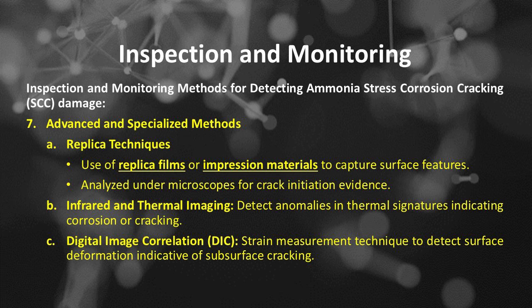Number 7 of inspection and monitoring methods for detecting ammonia stress corrosion cracking damage is advanced and specialized methods, which include: number A, replica techniques. Use of replica films or impression materials to capture surface features, analyzed under microscopes for crack initiation evidence. Number B, infrared and thermal imaging, to detect anomalies in thermal signatures indicating corrosion or cracking. Number C, digital image correlation, DIC, a strain measurement technique to detect surface deformation indicative of subsurface cracking.